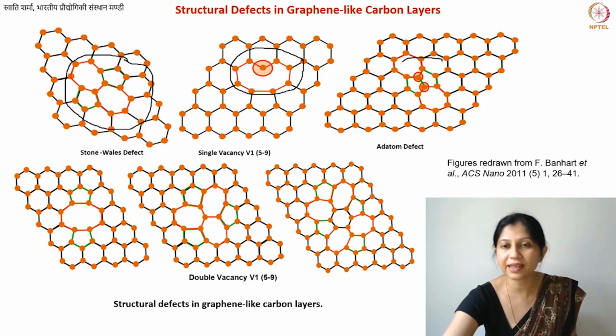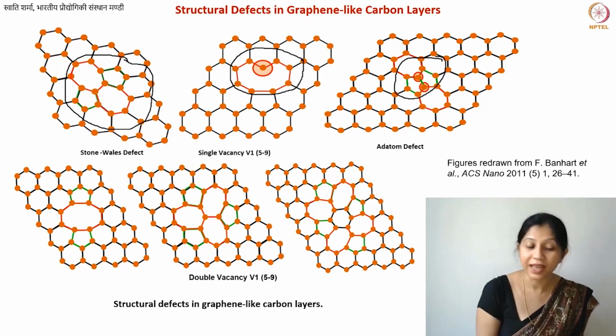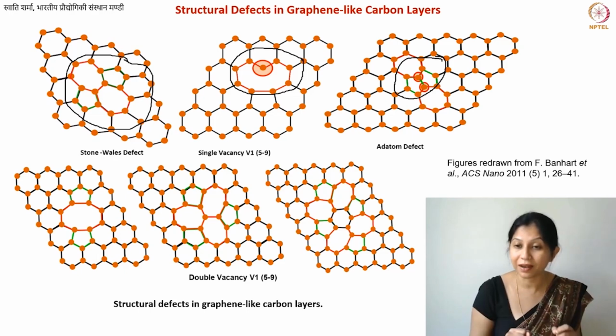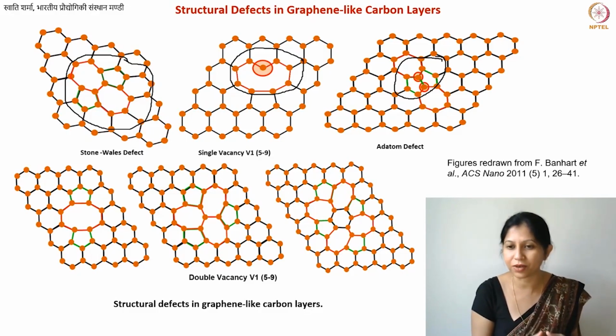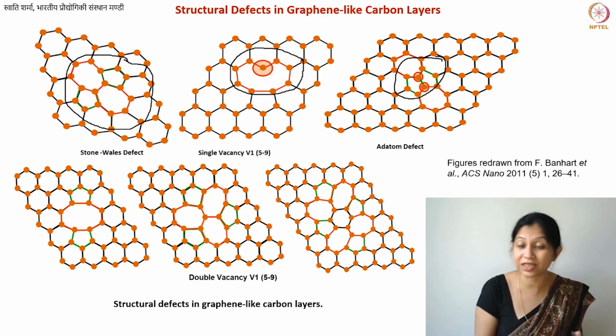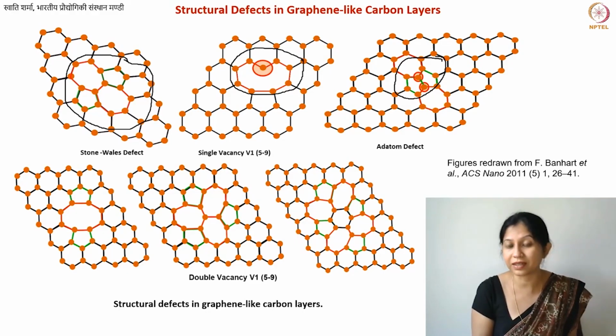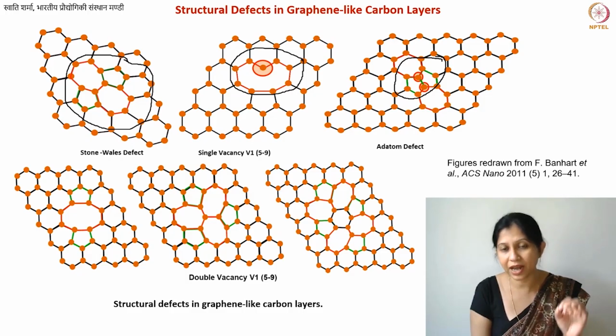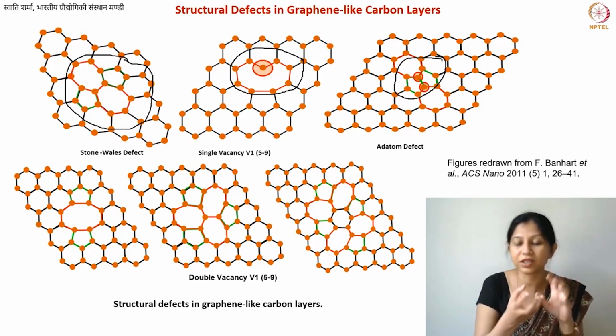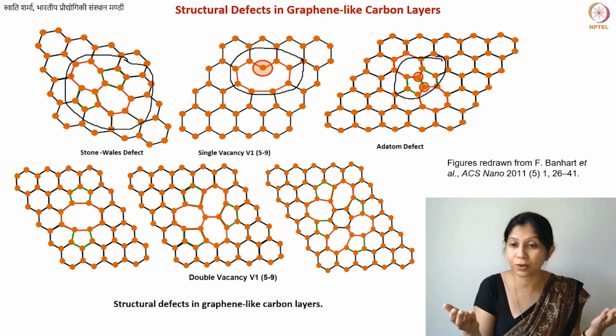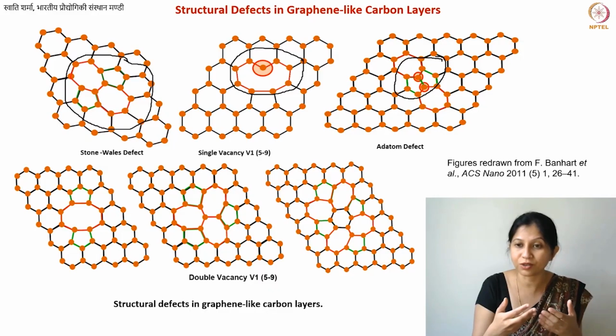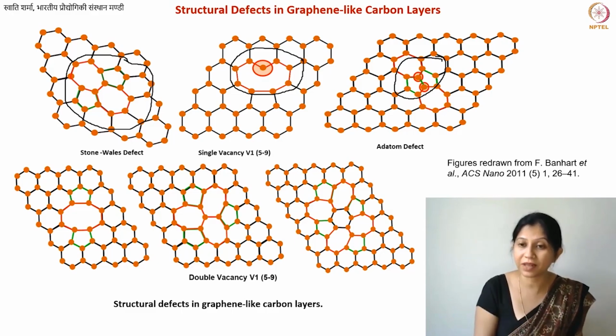In this particular case, this is kind of an interesting structure. There you have an adatom, so you have an additional carbon atom here. These kinds of defects you know in the context of 3D materials, even when you perform doping and you have interstitial atoms. So something similar, but here we have no foreign element. All the defects that we talked about are defects without the addition of any foreign atom, but it is just a carbon atom which, during its formation, somehow arranged itself in a certain position, and then maybe afterwards there was not enough energy for it to anneal out or to form a standard hexagonal type structure. So that particular atom now stays there.